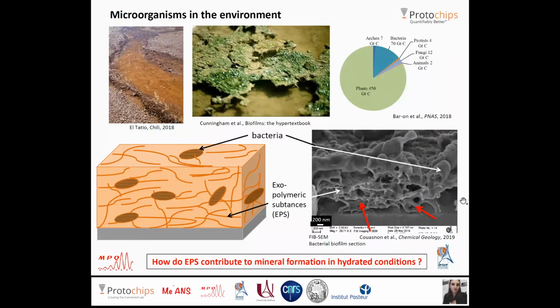When a biofilm is exposed to a solution containing dissolved metallic ions, the porosity and the negatively charged chemical functions at the surface of the organic matrix affect the concentration of precursors in solution and therefore the supersaturation with respect to a mineral phase, and they can induce the nucleation and growth of a mineral.